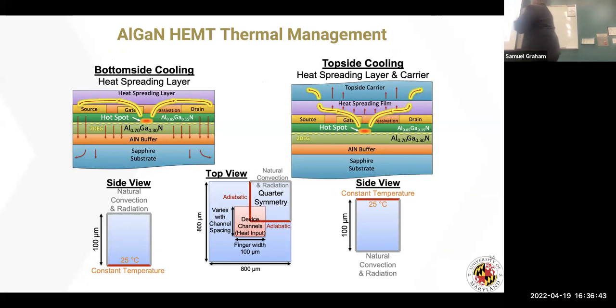So I'm going to talk about aluminum gallium nitride. I'm going to bring all these things back home as I run to the end. So one of the things that we started looking at here, this is some work being done with Sandia National Laboratories. Again, this hot spot at the drain side edge of the gate. What we're worried about is this gallium nitride on aluminum gallium nitride. There's an aluminum nitride buffer layer here that they used to grow when they place it on top of sapphire. So sapphire is aluminum oxide.